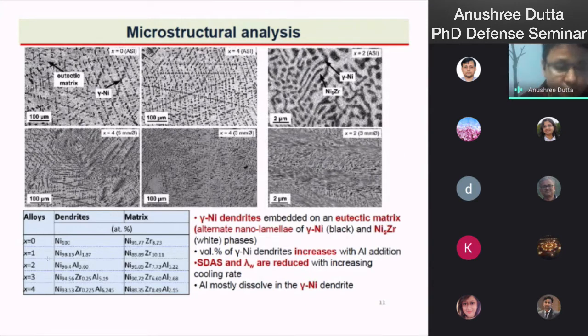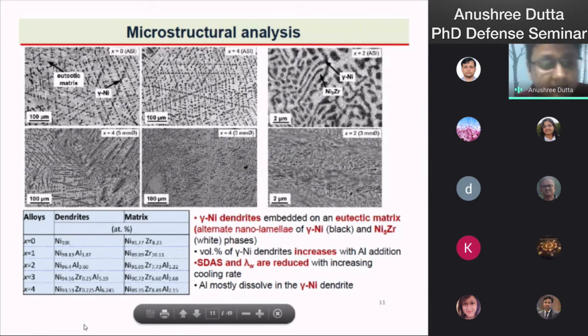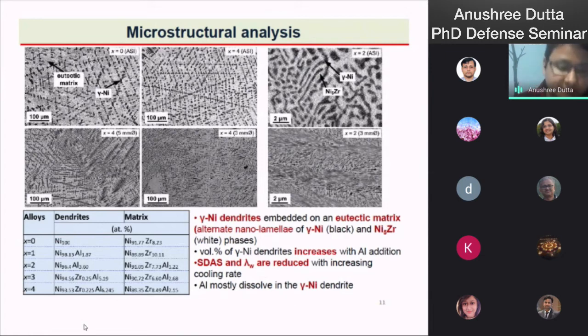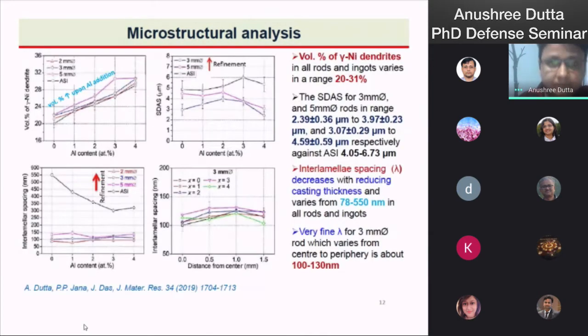The EDS analysis shows that the dendrites are mainly composed of gamma nickel, and a substantial amount of aluminum is present in the dendrite phase, whereas the matrix is mainly composed of nickel and zirconium. The aluminum dissolves mostly in the gamma nickel dendritic phase. The quantitative analysis shows the volume percent of the gamma nickel phase for all the ingots and rods changes from 20 to 31%, whereas the secondary dendritic arm spacing is refined in the smaller cast diameter rod, and interlamellar spacing is also refined in the smaller cast diameter rod.